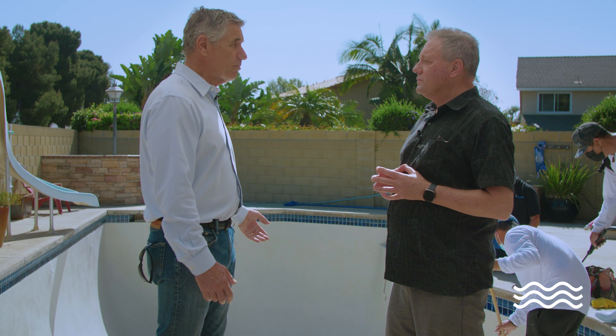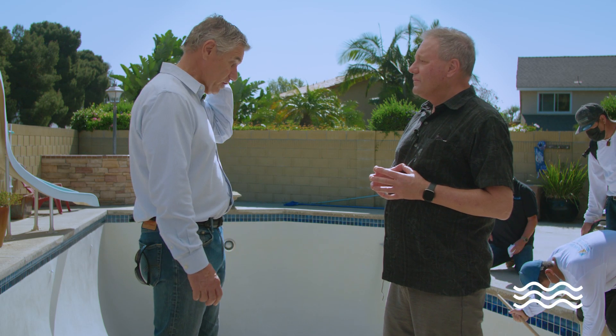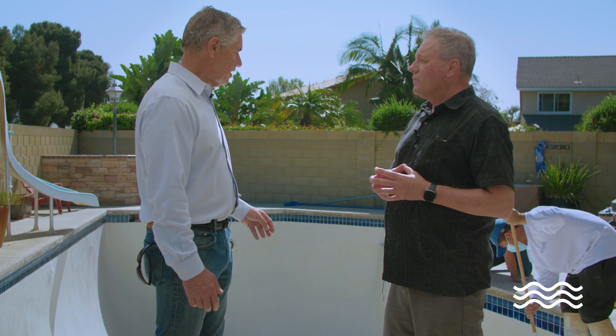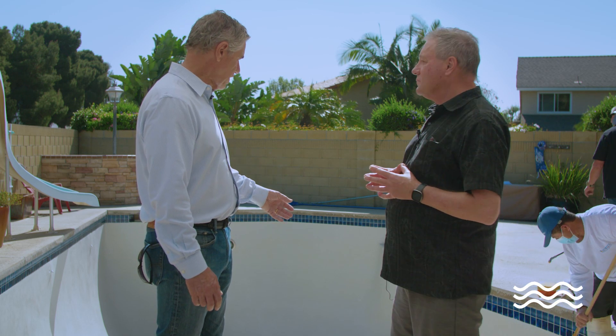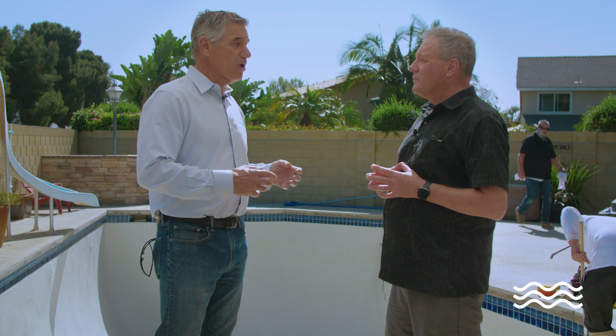Also, this works really good for check cracking and micro cracking. I have examples of pools — Bobby Altamirano just did a job where 60 mile an hour winds came up when they were almost done with a quartz job, and they came back to acid wash it. Craze cracking everywhere, where it was severe. And the pool builder's going, 'You're going to have to do this one over.' They put this product on, it filled the craze crack structure with a silicate. You can't even see them anywhere — nobody sees one crack in the pool, it filled them all in. Now, if you were to put this on a colored plaster job and fill it and it started check cracking on the upper side, and the product wasn't put on after the crack, that crack would be filled with calcium hydroxide and that will show. It would have to be done after the cracking event. So you still have your timing issues and all that.